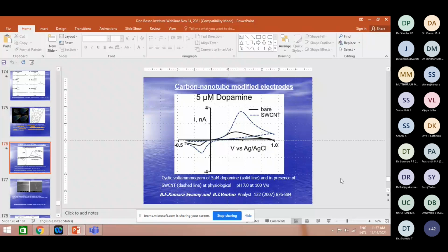Then I tried for 30 seconds, failure. Then I tried for 10 seconds, failure. Then one fine Friday morning, I did it with only one second of coating of nanotubes. Then we got a very good result. Then I did it for almost 2 to 3 weeks. Really very happy that it gave a very good result.